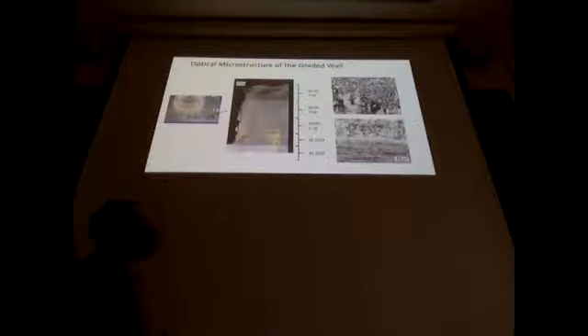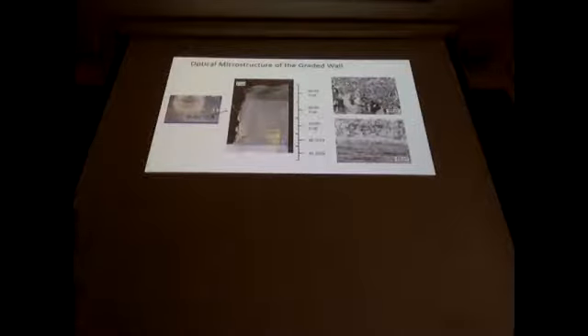We did look at a wall. One we sent back to our sponsor, but one we were able to keep. And so we did some microstructural analysis. Overall, when we built this on top of this aluminum 2024, it had pretty good bonding. We didn't see any gross porosity in it. We didn't see any cracking, so overall it looked pretty good. And here's our fusion area. These are just optical micrographs showing the etched 2024. Here's our weld and a little bit of heat affected zone.